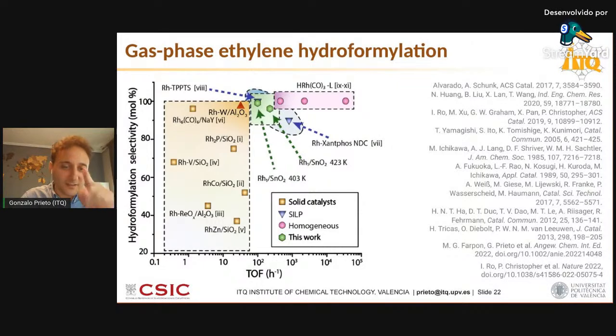For completeness, I have to add, and this is a data point that I added today for this presentation, because it is not part of this published plot, the red triangle dot there, because essentially in parallel to the revision of our manuscript, I think that both manuscripts were reviewed at the same time and they came out essentially at the same time over the last month. The group of Philip Christopher at UC Santa Barbara, they developed also this so-called dual site rhodium tungsten catalyst on alumina, which is also a fully inorganic catalyst, and that also delivers close to full selectivity for this process at slightly lower turnover frequencies than the rhodium single atom on tin oxide. But I just added these data points.